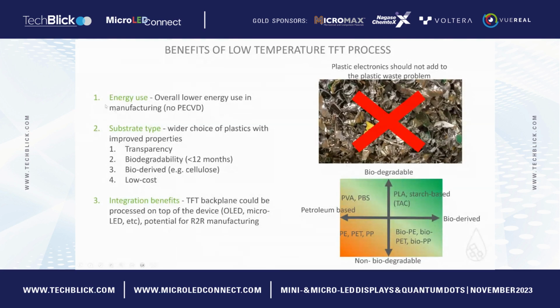So one of them is that with low temperature processing, you have a lower energy use in manufacturing. So you don't use PECVD, you don't have to go up and down to 360 degrees C. The substrate type you can use can be a very wide choice of different plastics. So you can choose your plastic for its transparency, so no birefringence, no color in it. You can even choose substrates because of their potential for biodegradability.